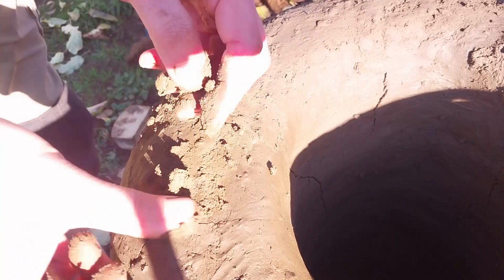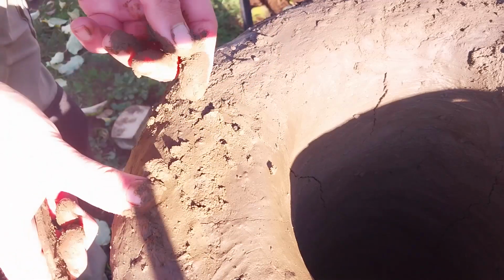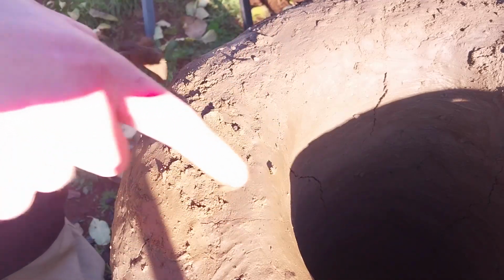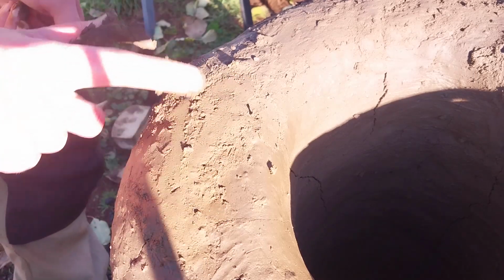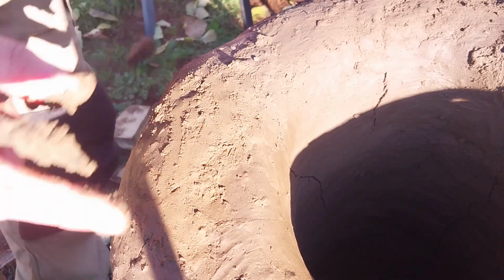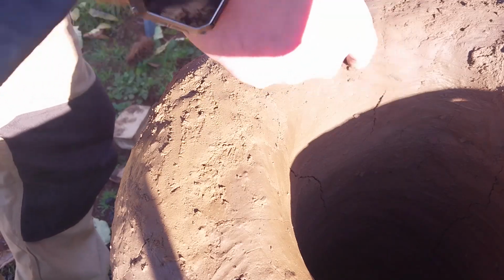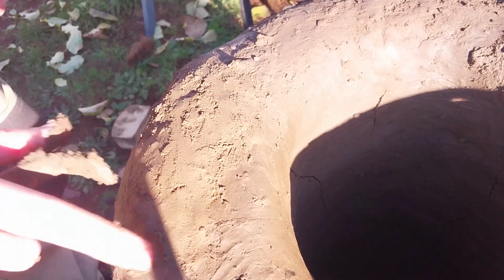The smaller ones that you see, the smaller ends I mean, most of this sort of crack, you would just want to leave. It's part of the drying process and it's natural, it's not going to form problems, especially at this point in the drying cycle. If after 10 days that hasn't widened, it's not going to widen.